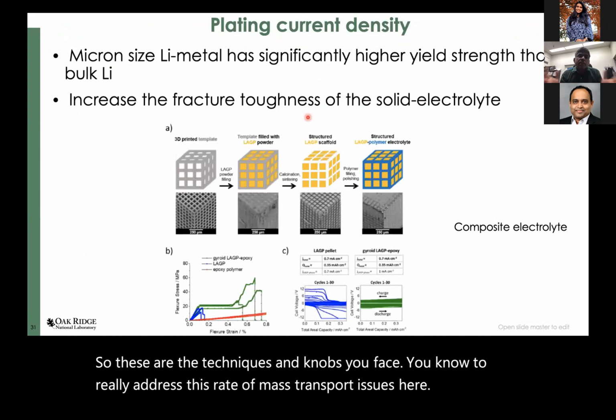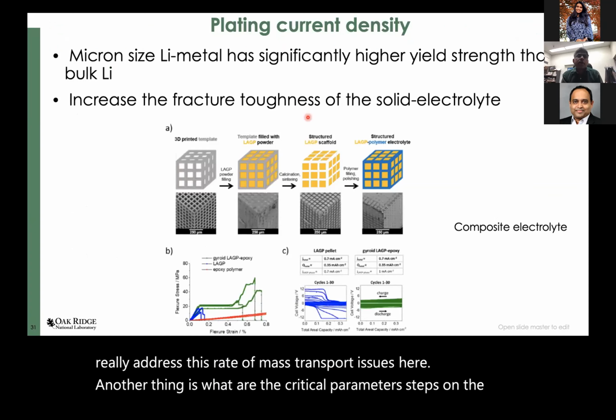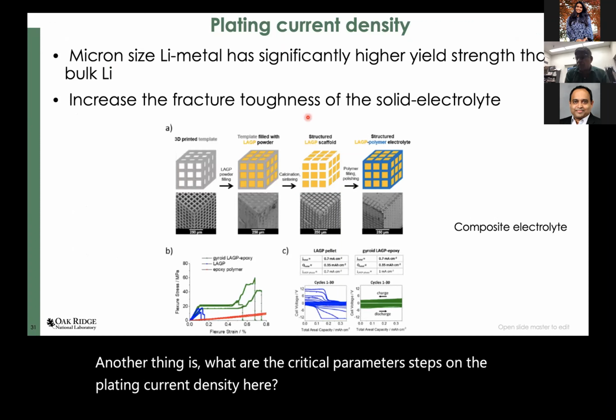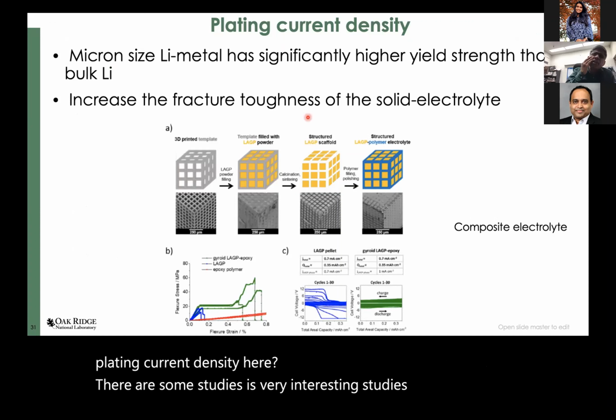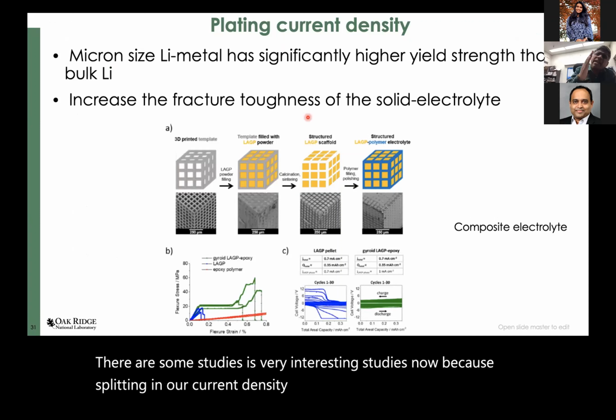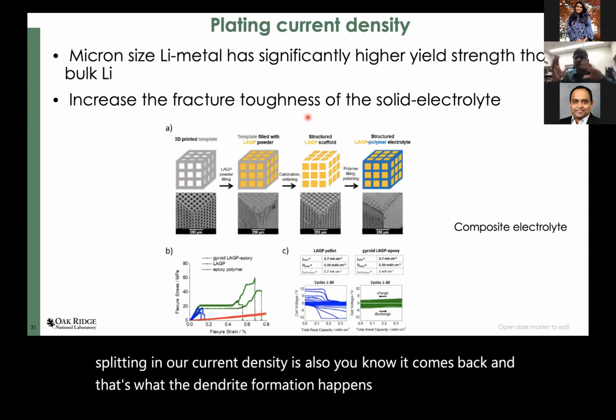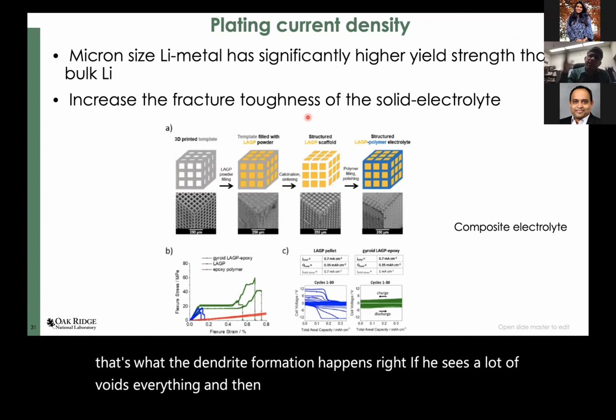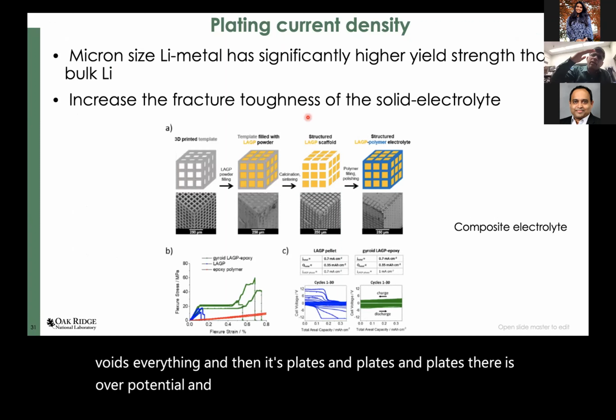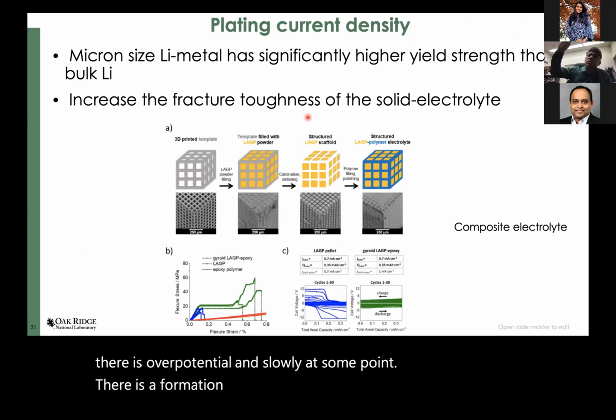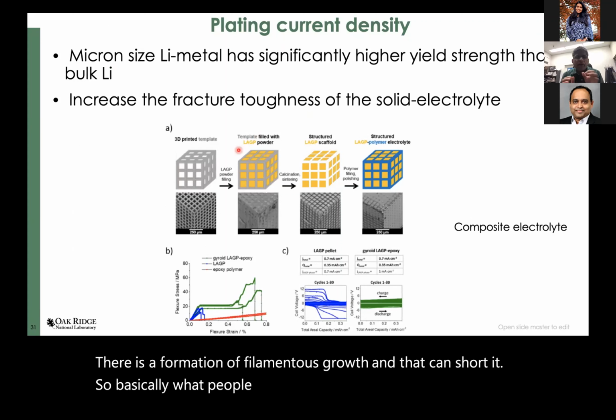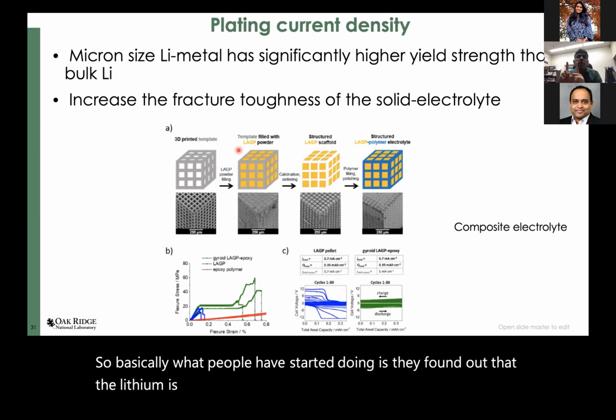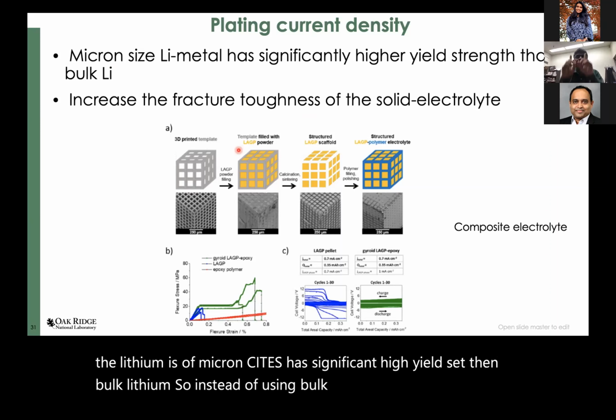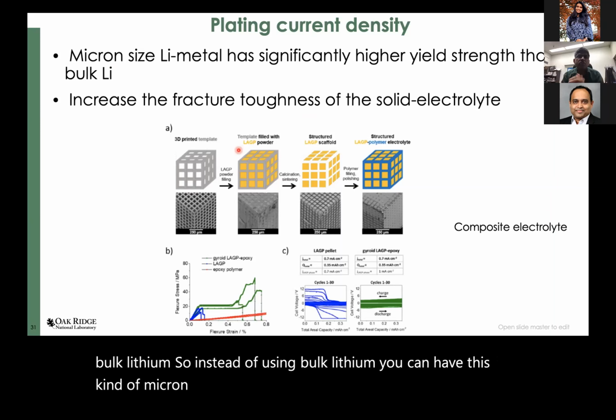Another thing is, what are the critical parameters based on the plating current density here? Now, there are some very interesting studies now, because plating current density also comes back, and that's where the dendrite formation happens, right? If you see a lot of voids, and then it plates and plates and plates, there's overpotential, and slowly at some point there is a formation of filamentous growth, and that can short it. So basically what people have started doing is they found out that lithium of micron size has significantly higher yield strength than bulk lithium. So instead of using bulk lithium, you can use this kind of micron size lithium, which has higher yield strength.